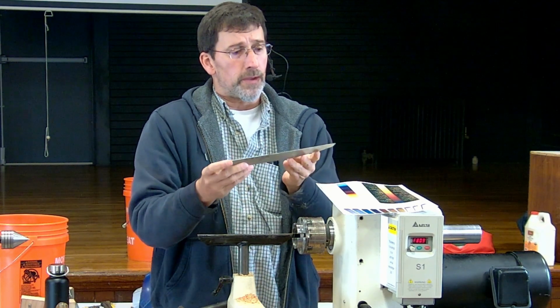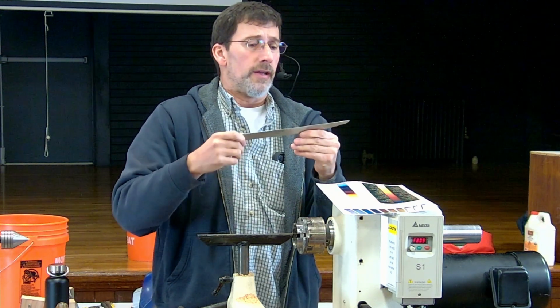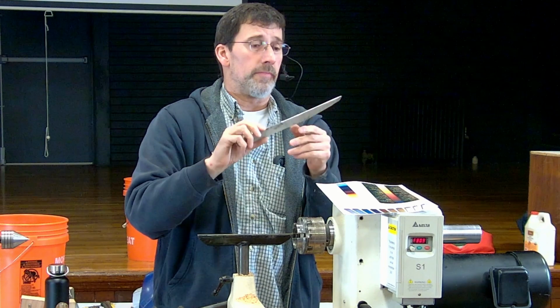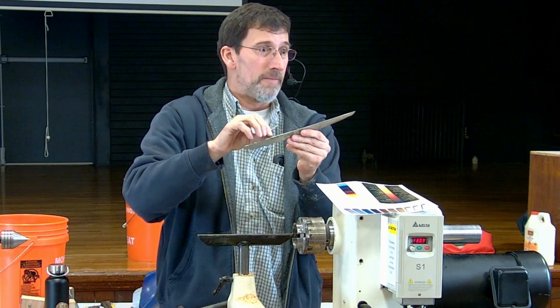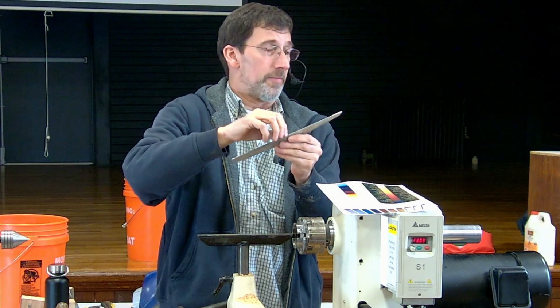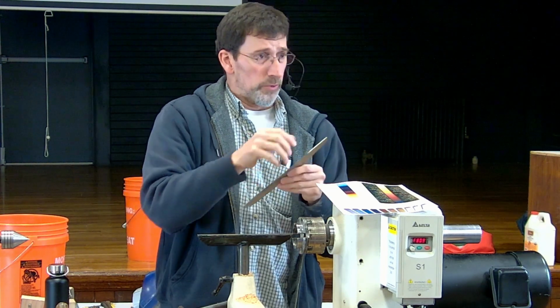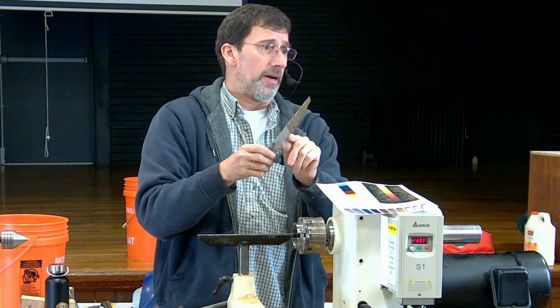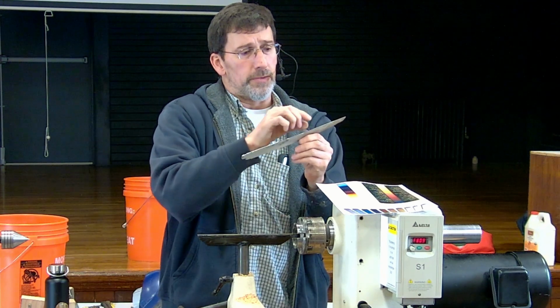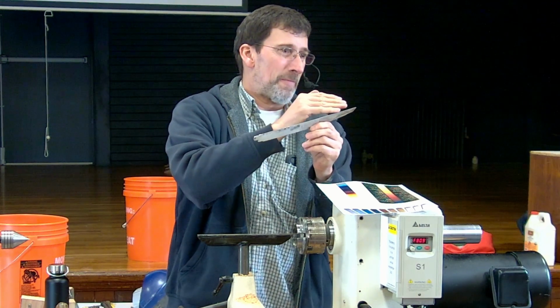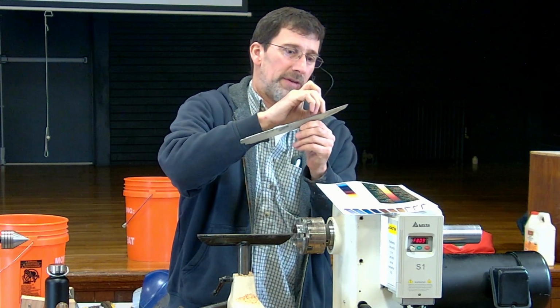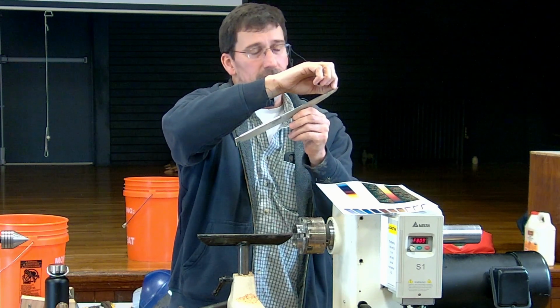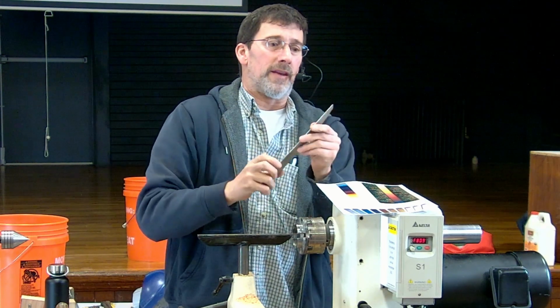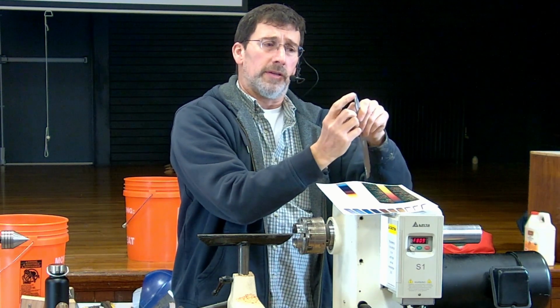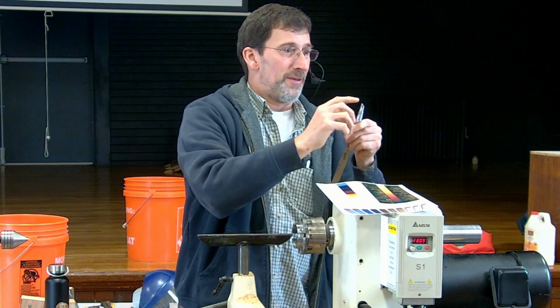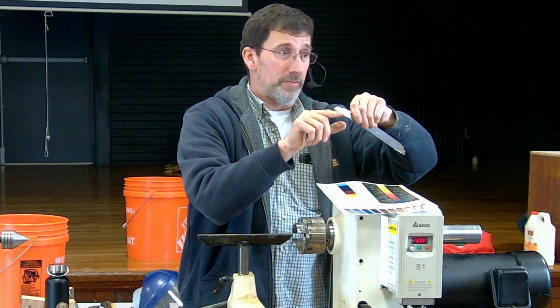One thing I'd like to note, when I make these parting tools, sometimes the saw blade, if on the label it says bimetal, it means the cutting edge is something like a cobalt tool steel, and then the steel behind it is simply carbon steel. So when you grind the teeth off, stop as soon as you get to the bottom, because you only have maybe 1/8 of an inch of the tool steel on that edge. And when you do the small little bevel cut here, don't go too far. Always keep it really close to that bottom surface.